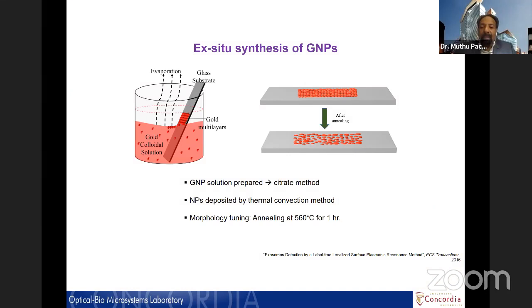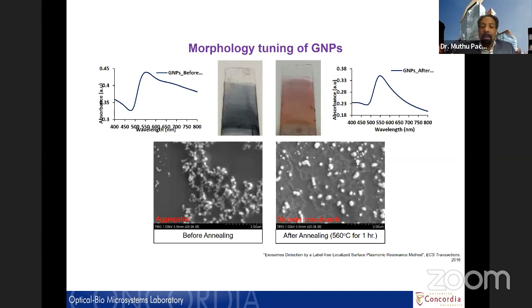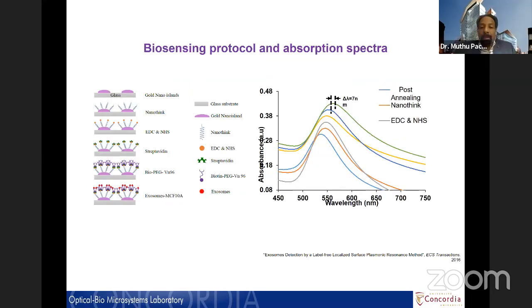And you can see some of the glass substrate with the PDMS microfluidic chip on that. These gold nanoislands are used for LSPR-based sensing of these exosomes. You can see some of these nanoparticles, as well as exosomes on top of that. This is a SEM of exosomes as well as nanoparticles on the substrate. And you can see how the plasmonic shift of these nanoparticles happens with the different stages of these bioprotocols. The final shift is what is important.